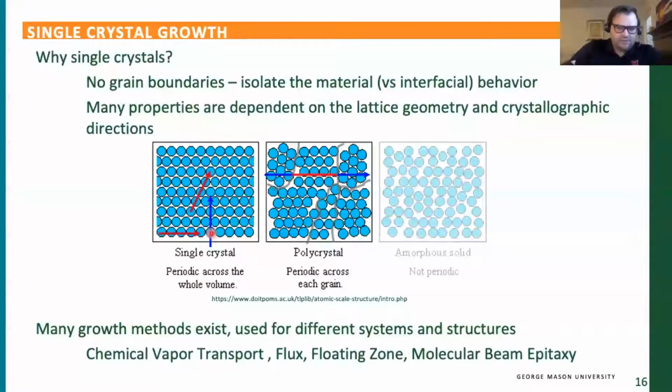In a polycrystalline sample, however, one crystal direction can contain grains of both periodicity orientations. Drawing a line across this sample, for example, it sees grains with both this blue and red orientations. Thus, we expect the results from a measurement performed on this crystal to have a muddled result that's like the average between both of these orientations together. In order to isolate the orientation dependencies and fully study the physics involved in these systems, this single crystal is necessary for us to have.